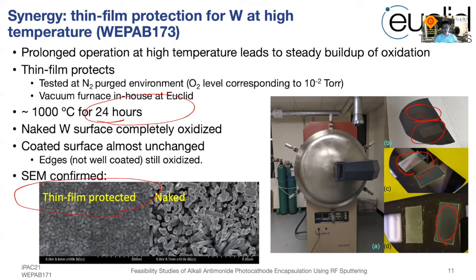But for the naked tungsten, it is very obvious that the surface has oxidized and formed a nanopillar structure. You can see the oxidation effect from the edges, and all those edges are degraded, and the tungsten oxide has fallen into debris off onto the silicon wafer base. So this means that the thin film, a proper selection of thin film, can protect the substrate from oxidation very effectively.